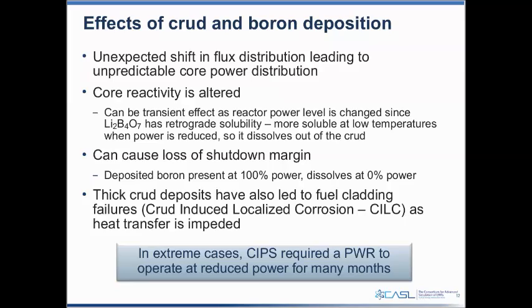This can also cause a loss in shutdown margin. The deposited boron is present when we're operating at full power, but it dissolves following a reactor trip at 0 power. So it's almost like we're operating with a control rod in the core at full power. Then when we reduce power, we pull out that control rod, making the core more reactive.